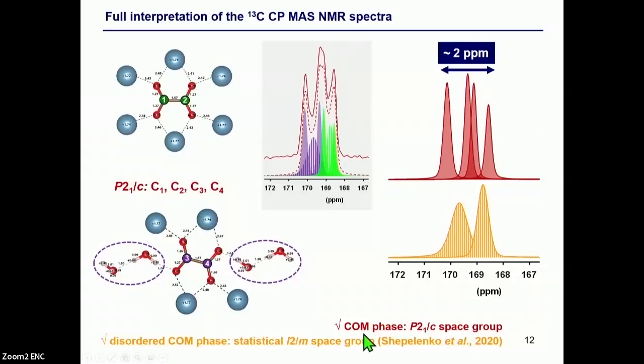And in fact, in 2020, a group of theoreticians in Israel proposed a disordered COM phase, which is based only on DFT calculation, no proof, no experiment, and so on. But the idea is that they introduce a statistical space group, which is completely different from this one. And in this case, there are only two inequivalent sites for carbon-13. And as we have disorder, it could be the origin of the broadening of the peaks.